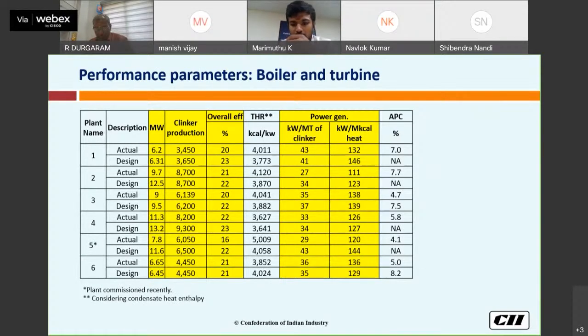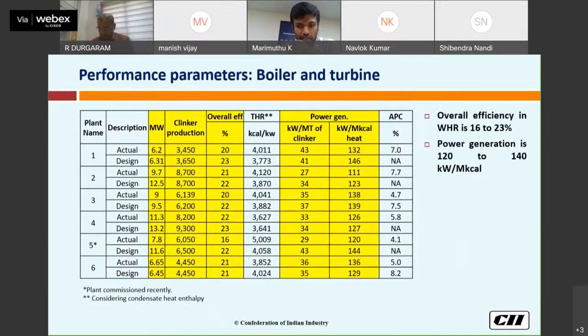Then this table gives figures on boiler and turbine parameters. The overall efficiency of the system based on the different cement production capacities is illustrated. It is in the range between 16 to 23%, and power generation is around 120 to 140 kilowatt per million kilocalorie, and the turbine heat rate which we found is around 3,627 to 4,120. This is the turbine heat rate calculator, based on considering the condensate heat enthalpy.